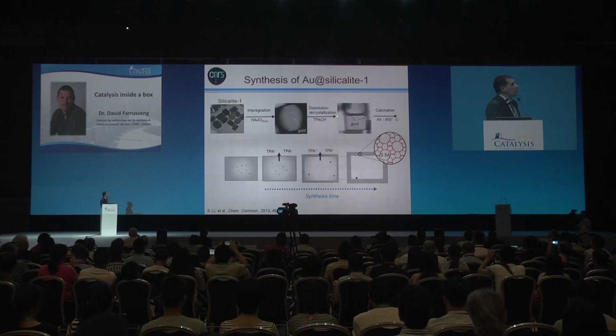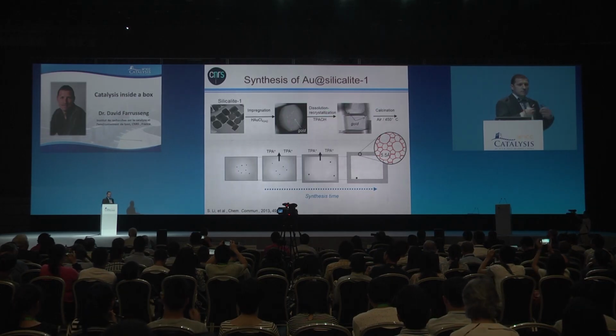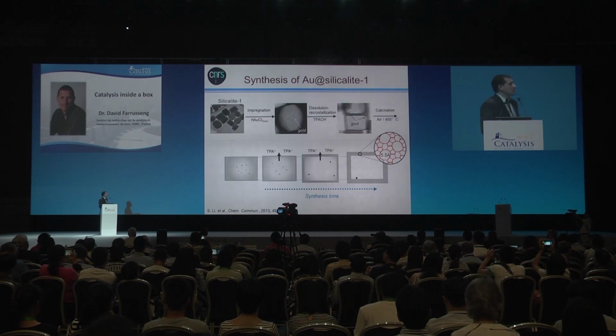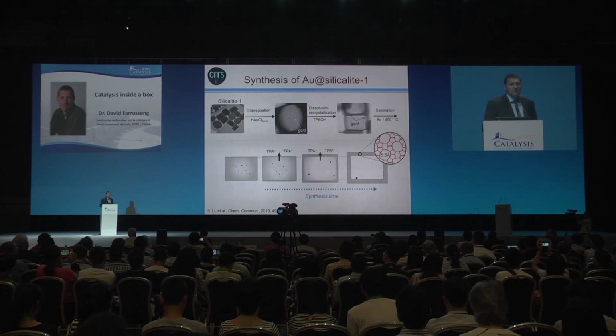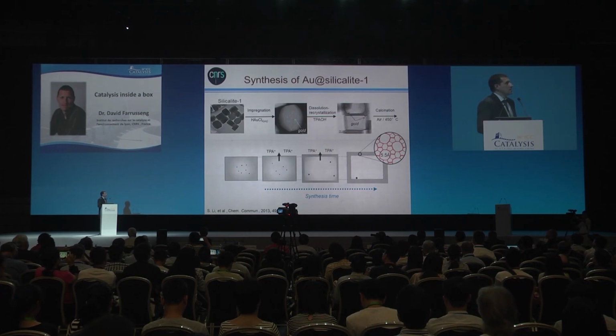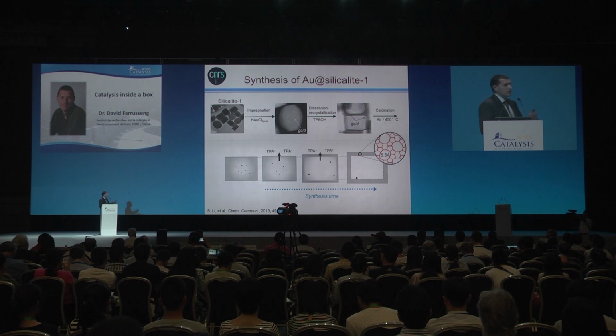And then we apply the dissolution recrystallization process. We make empty the zeolite. And surprisingly, what we found is that in each cavity, we find one single particle in each cavity. We could hardly believe it when we saw that for the first time, actually. And what happens is that we have the particles here, and progressively the matter is going out.